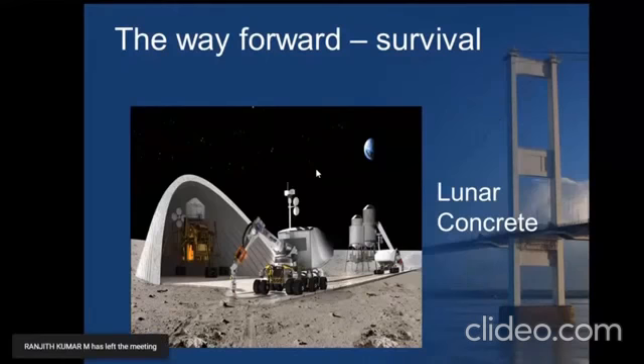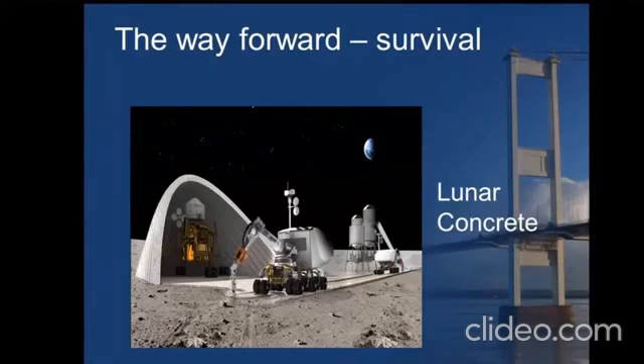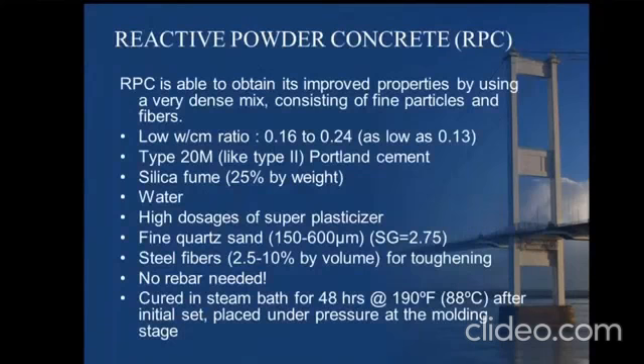So this is just a note on what is happening in the material aspect, but not into the specific material combinations that go into a lunar concrete. The next thing is also a very interesting concrete, which is reactive powder concrete. Reactive powder concrete has been used in cooling towers and in high-rise buildings. This is a notable concrete where, again, coarse aggregate is totally eliminated. But the strength that can be achieved is from 200 to 800 MPa. 800 and 600 MPa concretes are already in practice abroad.